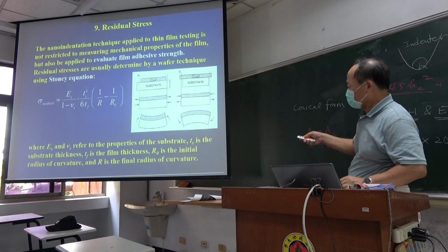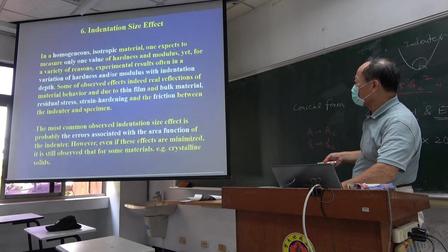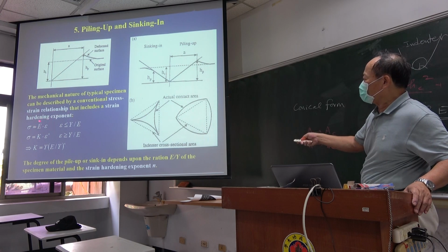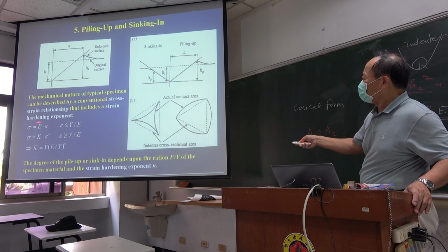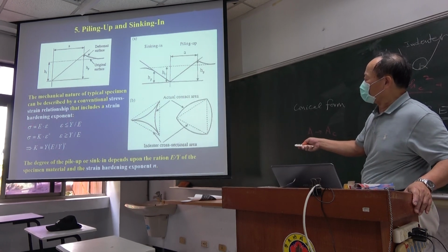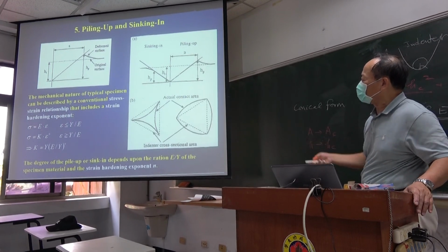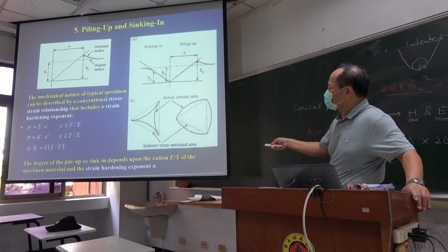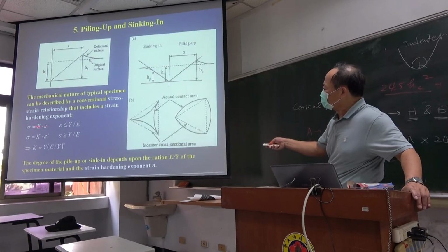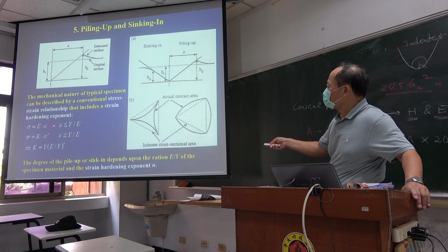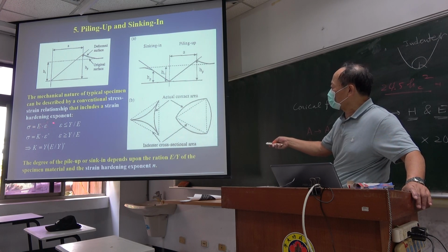Okay, here, if you're operating, Y is the yielding stress, epsilon is your strain. Sorry. Epsilon is your strain. E is your Young's modulus. Here, if you're operating in the elastic deformation area, you'll find that your stress sigma and your strain epsilon have the linear proportionality. I mean sigma equals E times your strain, where E is your Young's modulus.